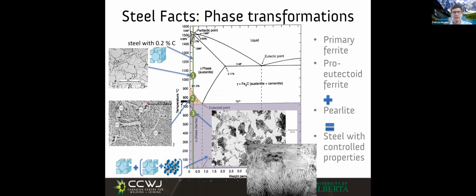If you get deeper into the metallurgy, you'd say, why does the ferrite appear in the austenite grain boundaries? That relates to this issue I mentioned, that at the grain boundary, the atoms don't really know what side to what grain they belong, and they have a relatively higher energy. So when it's time to transform, the first things that transform are the things that have this high energy that are in the grain boundaries.